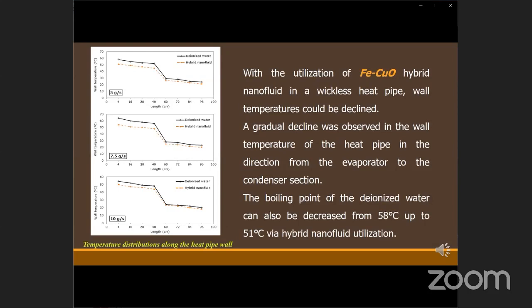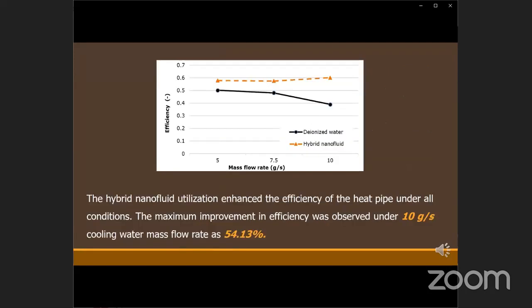With the utilization of iron copper oxide hybrid nanofluid in a wickless heat pipe, wall temperatures could be declined. Also, a gradual decline was observed in the wall temperature of the heat pipe in the direction from evaporator to the condenser section. The boiling point of the deionized water can also be decreased from 58 Celsius up to 51 Celsius via hybrid nanofluid utilization.